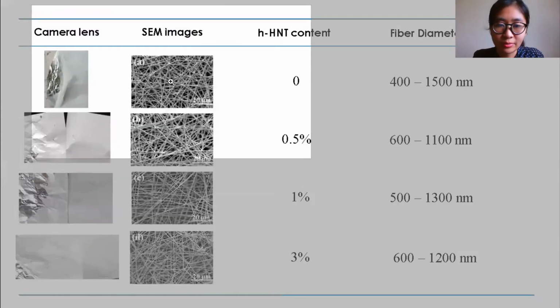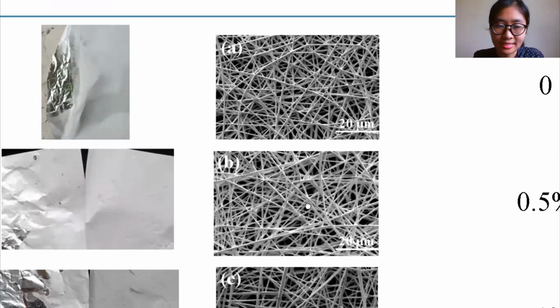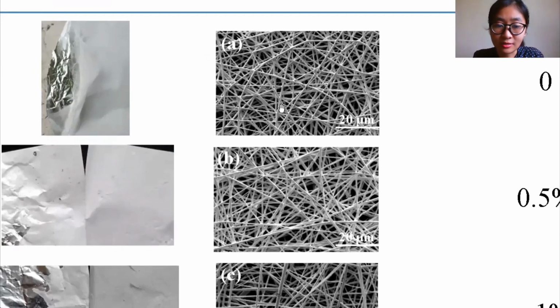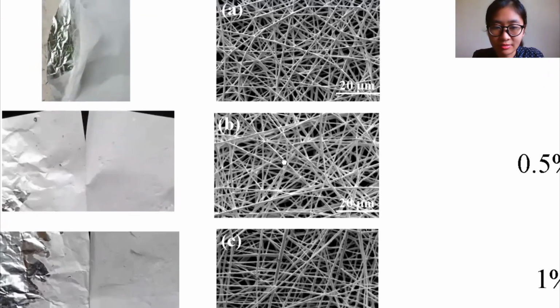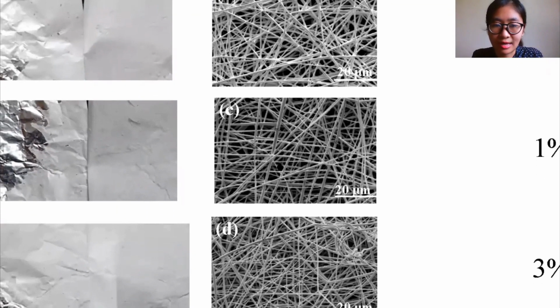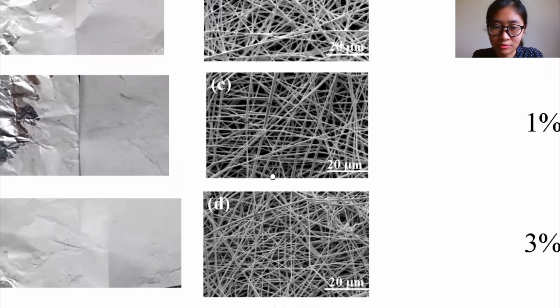Fiber morphology for pure PLA was observed to be smooth and densely packed. This may be due to the use of a conductive collector, which helped dissipate the charges and reduce the repulsion between fibers. On the other hand, the morphology of the polymer clay composite membranes was observed to have a slightly rougher, uneven surface with improved diameter uniformity.